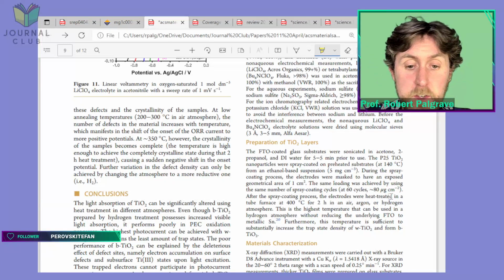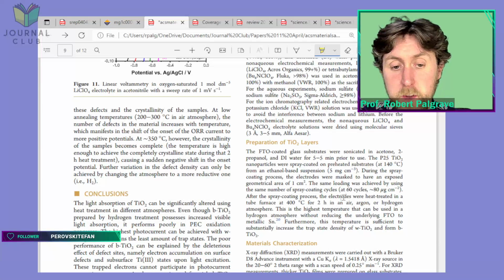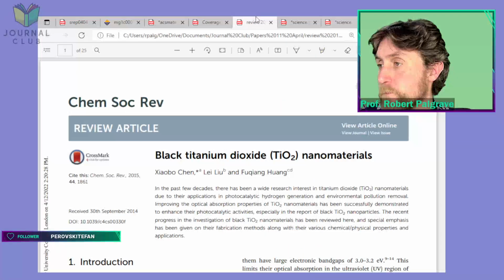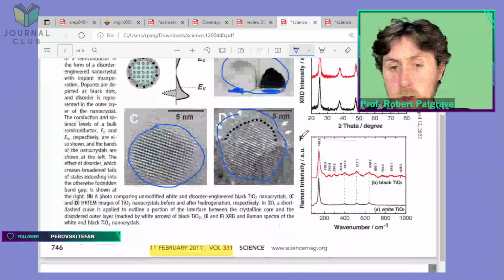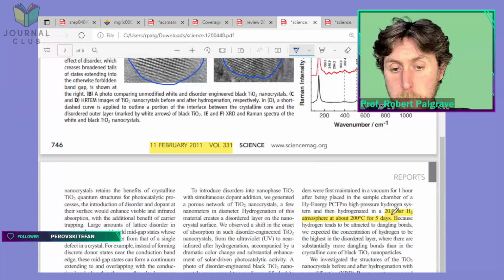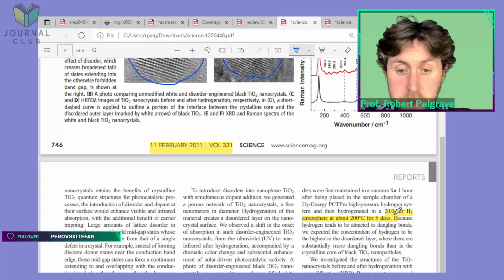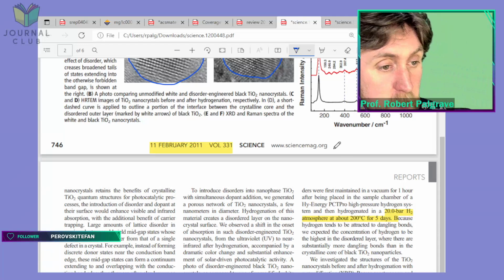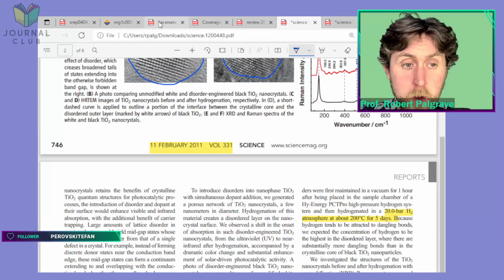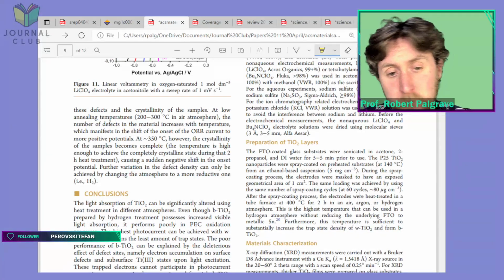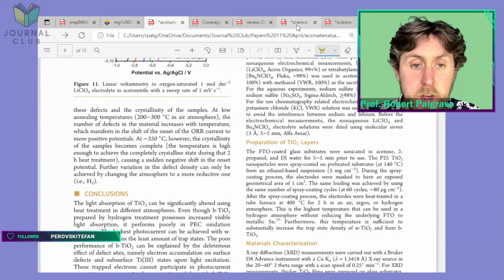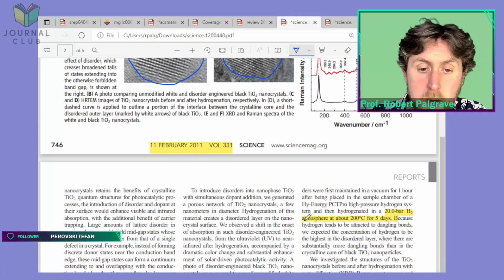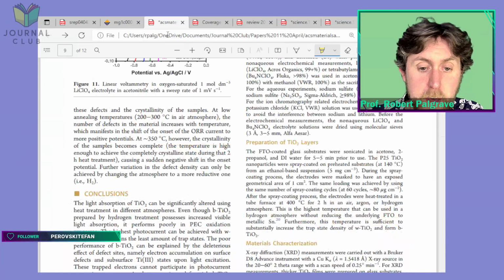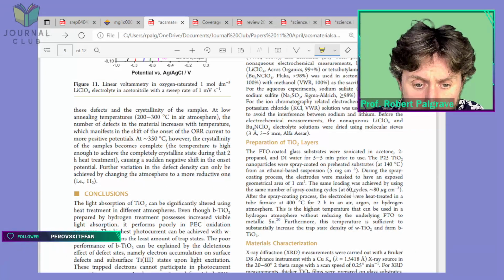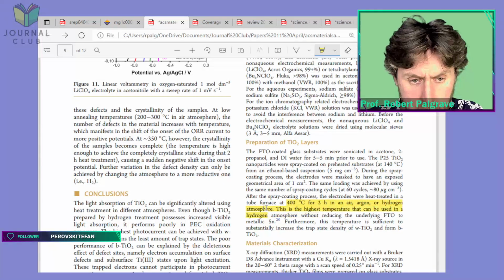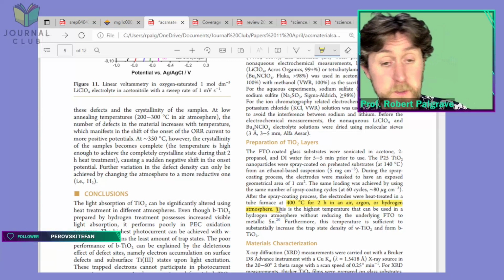Now, if you've been here since the beginning of the stream, or watching since the beginning of the video, you'll remember back in the original paper, they used quite a different method to produce their black TiO2. So they used 20 bar of hydrogen, so that's 20 atmospheres. I think the guys in the current paper we're looking at were using one bar. They just say in a hydrogen atmosphere. I'm guessing they just use a normal pressure there. But these guys use 20 bar, and they did it at 200 degrees for 5 days. Whereas here we have 400 degrees for 2 hours in hydrogen. So lots of differences there already.